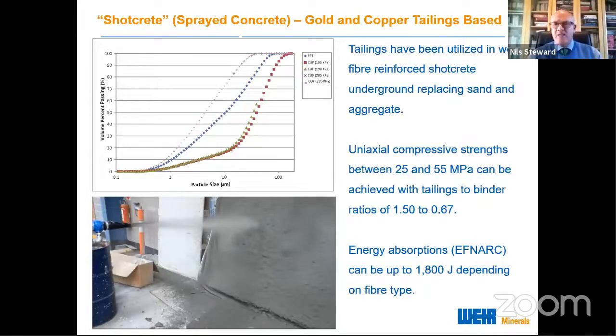And an EFNARC result, or a French panel result, some people might know of it as, is about 2.5 to 3 times the energy absorption you would get with an Australian round determinate panel. You do have to use accelerator with this. So again, we've actually replaced a sand, we've replaced it with a tailings, and we're actually able to achieve up to 40% savings in costs to the mine by utilizing their own tailings.